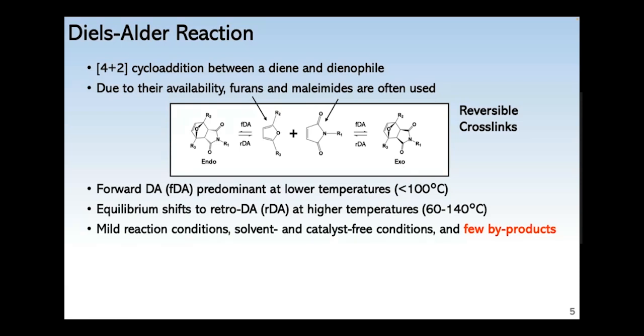So talking about a specific temperature range at which these occur can be ambiguous, but in general, the forward reactions remain predominant below 100 C, and then the reverse reactions will become more active past 60 C. Some of the generally cited advantages with this chemistry are its mild reaction conditions. You just need heat to stimulate it, and the fact that it can occur with most of the materials that can do this reaction without any solvent or catalyst to boost it. And then a few byproducts, which I've put in red because these side reactions become more significant at the temperatures where you can perform retro Diels-Alder.